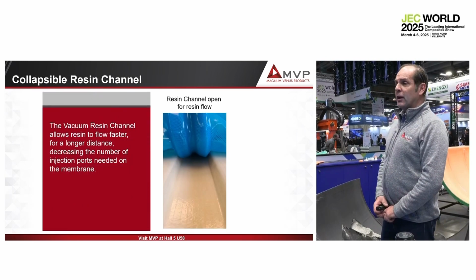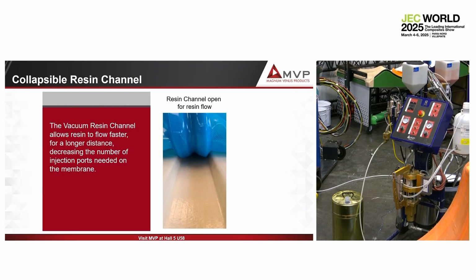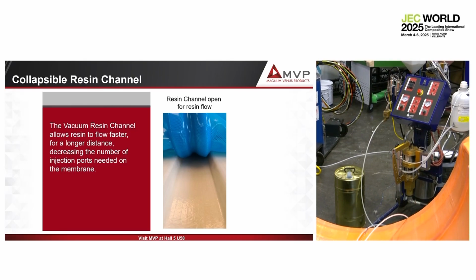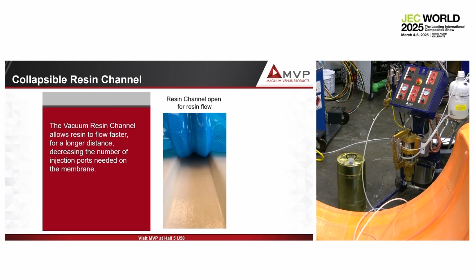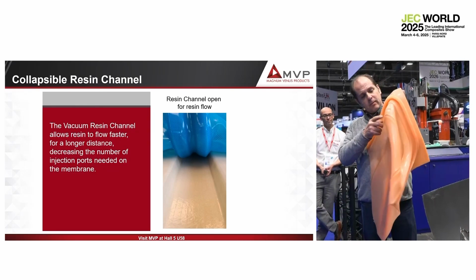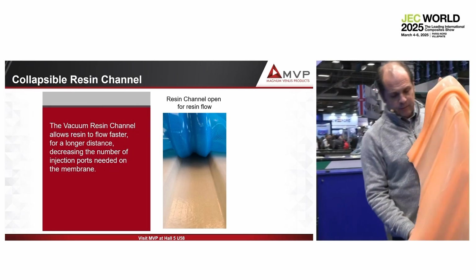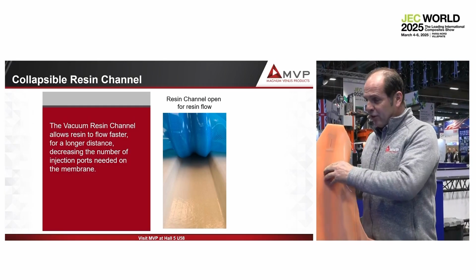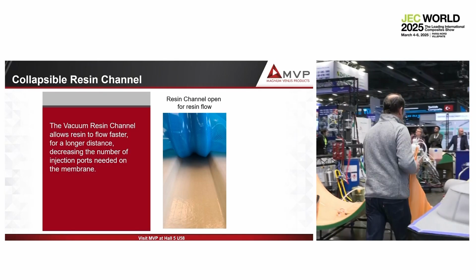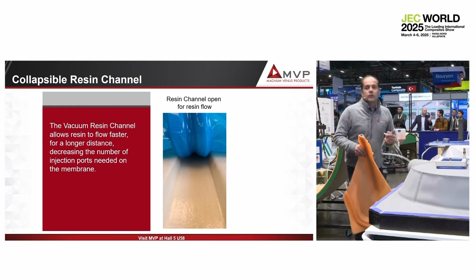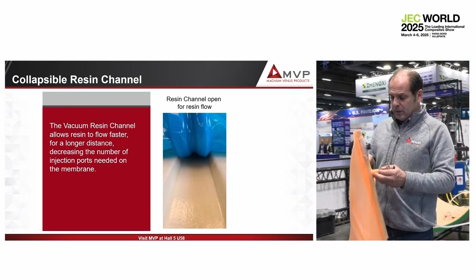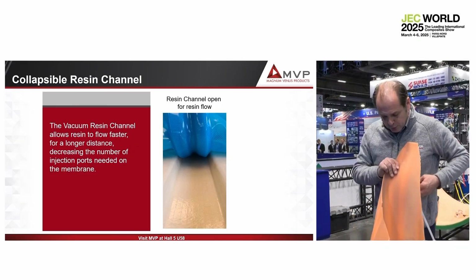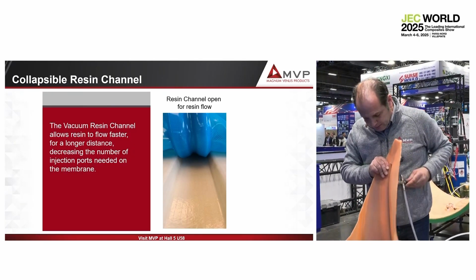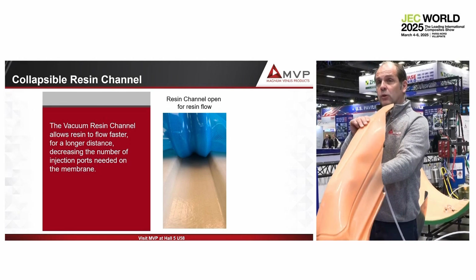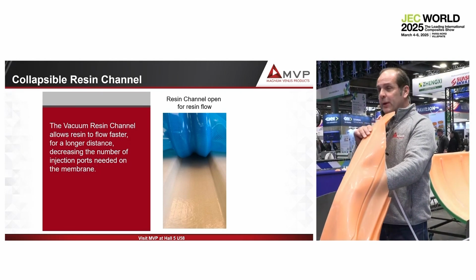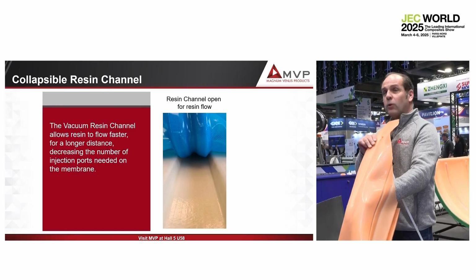How is the collapsible channel working? We have a membrane like that. Silicone membrane, 3 mm thick, normal. Groove system, vacuum channel, and the resin channel. The resin channel is working like that. We apply a second vacuum into the resin channel, and when we pull the vacuum, this is what happens. We suck the vacuum into the groove, and we create the groove. In this case, the resin will flow inside the groove.